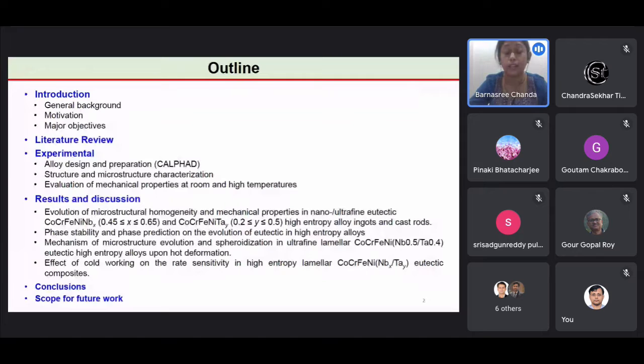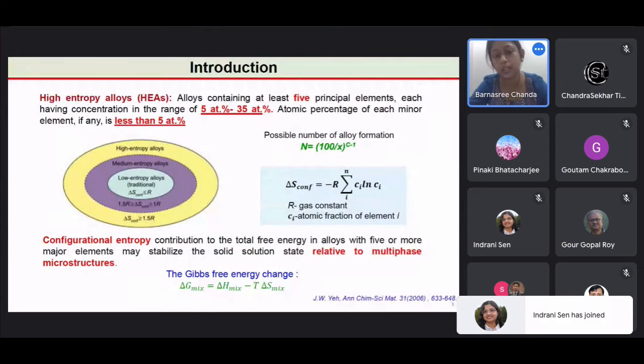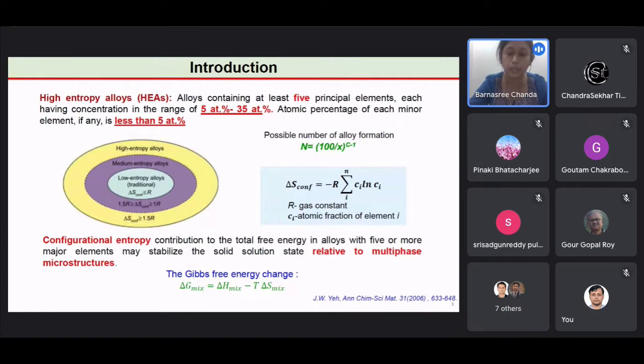High-entropy alloys are defined as alloys containing at least 5 principal elements and having concentration in the range of 5 to 35 atomic percent. And if there are any minor elements, their concentration should be less than 5 atomic percent. On the basis of configuration entropy, high-entropy alloys are generally defined as having configuration entropy greater than or equal to 1.5 R. The schematic shows how the alloy world can be divided on the basis of configuration entropy.